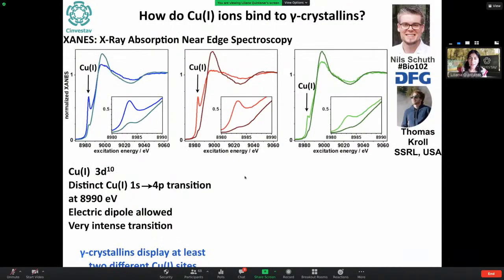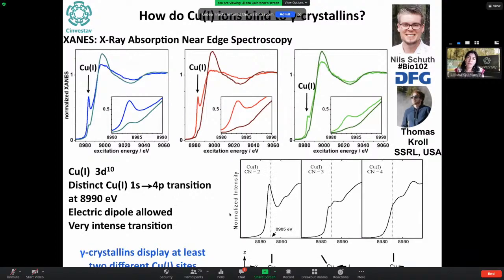And thanks to Dr. Nils Schuth, who's a postdoctoral fellow in my group with a DFG fellowship from Germany, and he has a lot of experience with X-ray absorption spectroscopy techniques, we could also, in collaboration with Thomas Kroll at Stanford, collect data on these same samples I showed you in the EPR, where we see a decreased spin quantitation. And we could confirm the presence of this very sharp feature in the pre-edge, that is ascribed to a 1s to 4p transition for copper-1.